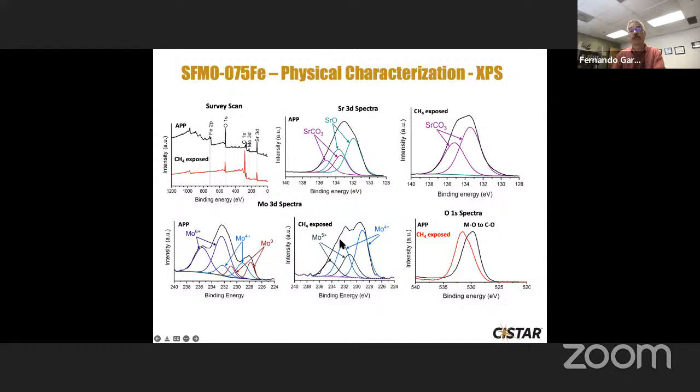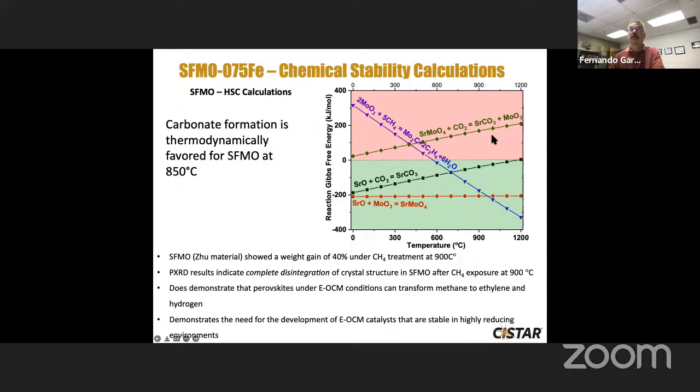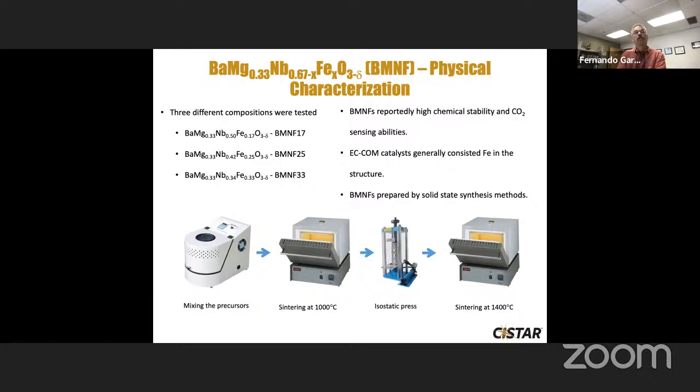So if you look at the stability of the binary oxides, again, you are fighting the Gibbs free energy of formation of the carbonates against these negative reactions here, also forming the strontium molybdate phases. And so this is driving the decomposition of this material. So unfortunately, this material is not thermodynamically stable for the desired reactions. So we explored a number of materials